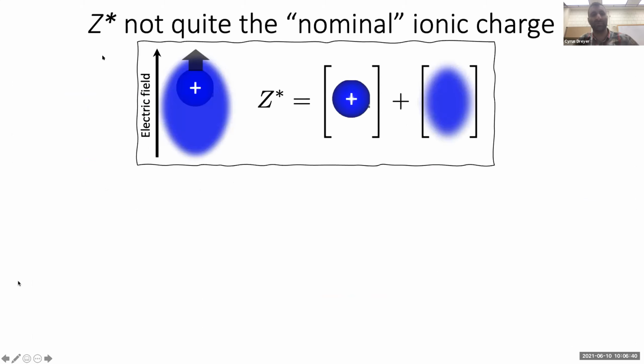So what we know about the Born effective charge is, as I said before, it's not a static charge, and it's not quite corresponding to the nominal ionic charge that we might expect for a material. And the reason, of course, is that we might have some electrons that are tightly bound to a nuclei forming what is basically a rigid ion. But we'll also have some less tightly bound electrons whose charge density will deform in the field, and those will both contribute to the Born effective charge.